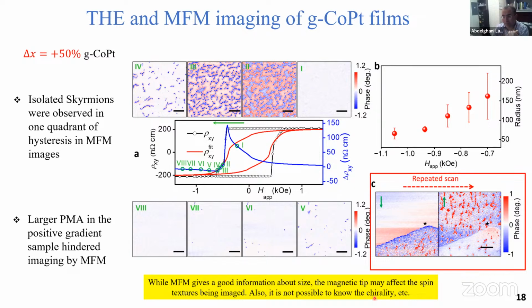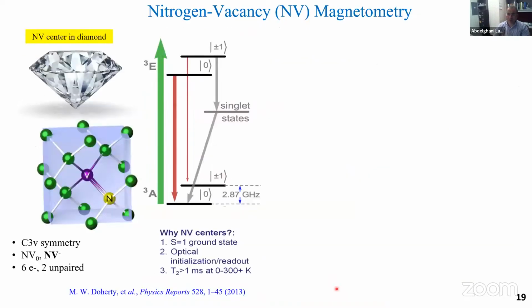the magnetic tip may affect the spin textures, and also you cannot know the chirality of these spin textures. That's why we use NV magnetometry.